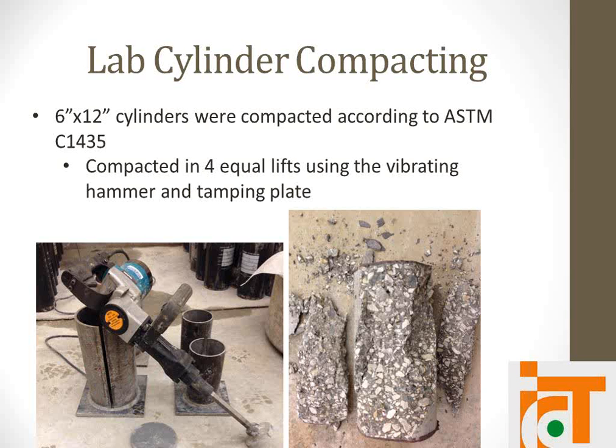So then creating cylinders in the lab, you use a vibrating hammer. What's on the tamping rod currently is a 3.5 inch diameter tamping plate to make 4x8s, as well as the circular one on the bottom, which is about 5.5 inches, to make 6x12s. Currently the ASTM spec only specifies 6x12 inches, but we're also looking at 4x8s. I'll show some results on that.